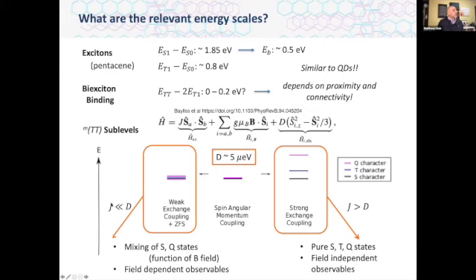In the normal case, the interchain or interchromophore interactions are weak, and our energy levels tend to be close to degenerate, and they split and mix in ways we don't have to describe in too much detail now. But let me just say that this is the normal case we find in solids, where you have weak exchange coupling, and you tend to mix states of the same parity but different net magnetization. So the quintets and the singlets will start to mix, so spin won't be a good quantum number, sorry. But anyway, the point is that these energy levels will be very close to each other. And it's again set by a zero field splitting parameter, which is on the order of 5 microelectron volts. So we have half a volt for the exciton, 100-ish millivolts for the biexciton, and then for the MTT sublevels, we're on the order of just a few microelectron volts, so way, way less than kT.